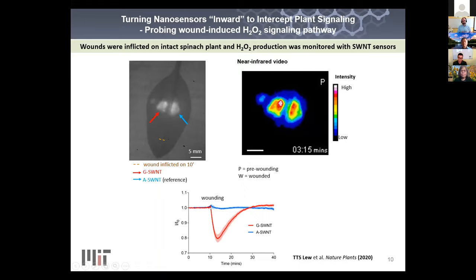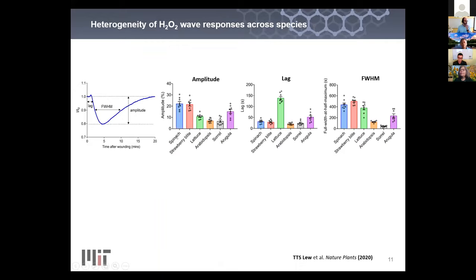If you wound it, these are experiments that are well studied. And it turns out that you get a very characteristic wave. This wave we've been mathematically describing, it's very unique to wounding in the plant. It turns out it has an analytical mathematical solution. You can measure it in different plants. Its amplitude, full width at half max, and the speed of the wave, also called the lag, seem to vary for different crops.